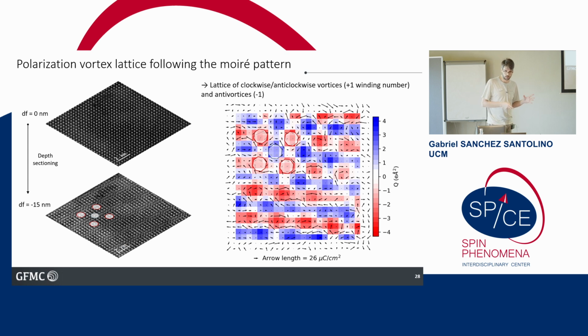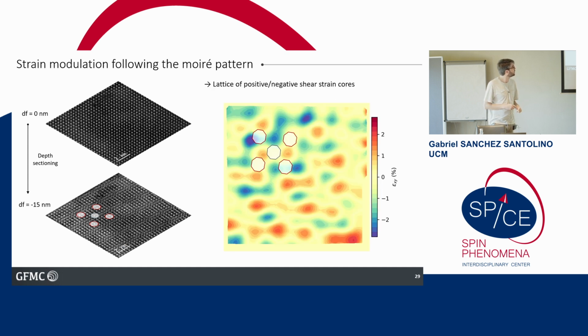And if we study not only the displacement of the titanium from the center of the unit cell, but the lattice parameter and the distortion of the unit cell itself that I showed you in the beginning, when we have this polarization, the unit cell is also going to be distorted. We get this kind of strain landscape. This is coming from the structure of the unit cell, so from the barium lattice only. And we have this shear strain, this kind of twisting strain, and we are going to have a lattice of positive and negative cores of the shear strain that are just in the middle of the highly coincidental sites.